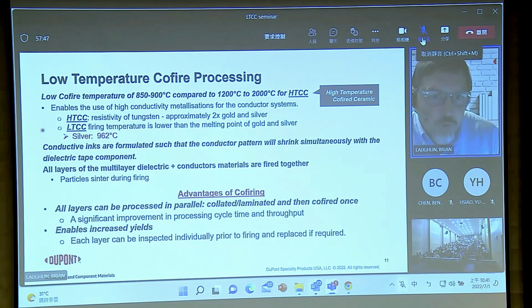The low temperature co-firing, because there's a glass-aided sintering of the ceramic, we're below the melting point of gold and silver. So you can use those very high conductivity, high reliability materials. We tend to focus on gold and silver because they are noble metals and can be fired in air. There are ways to design processes to utilize copper metallization, but it takes nitrogen firing, which is not a common thing to have in an LTCC shop.